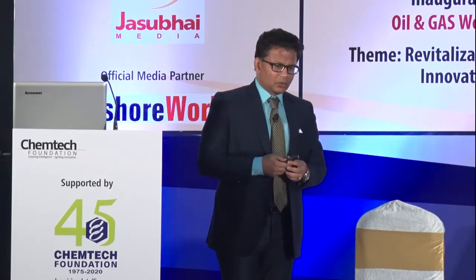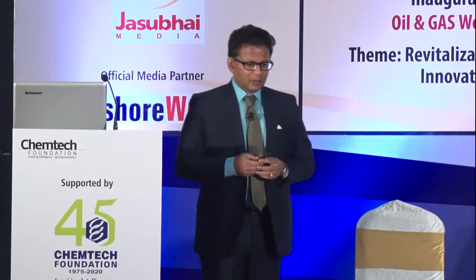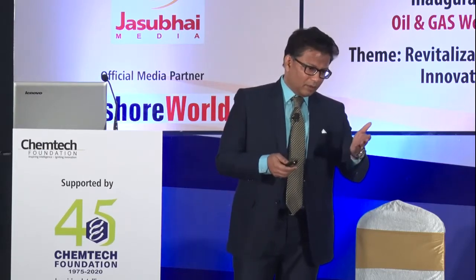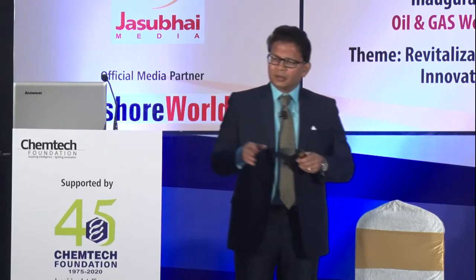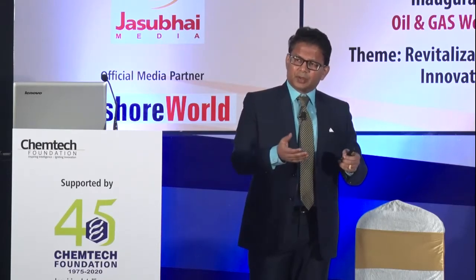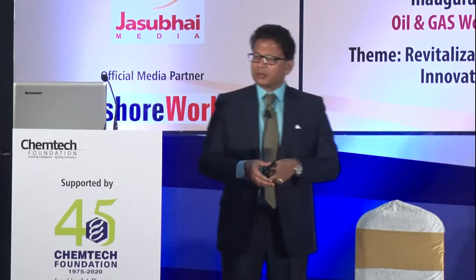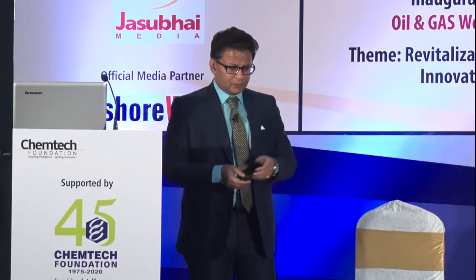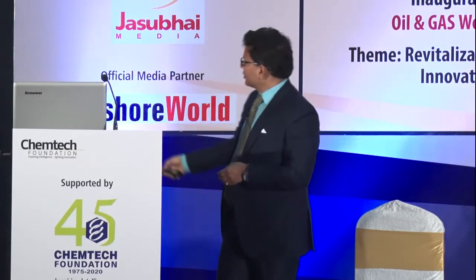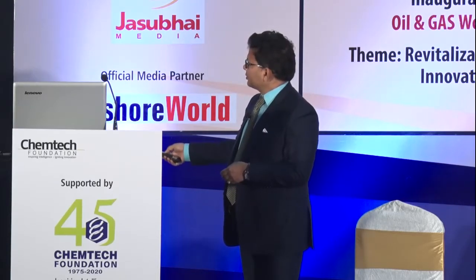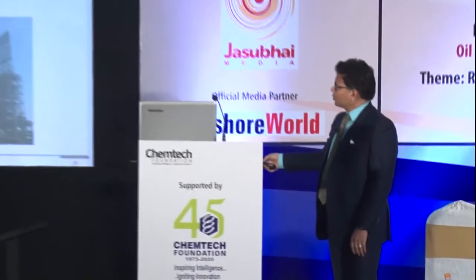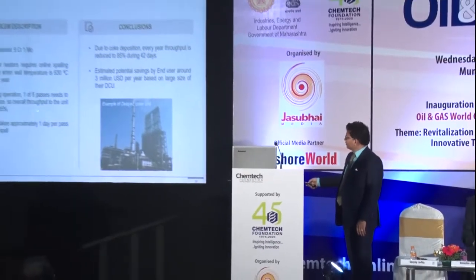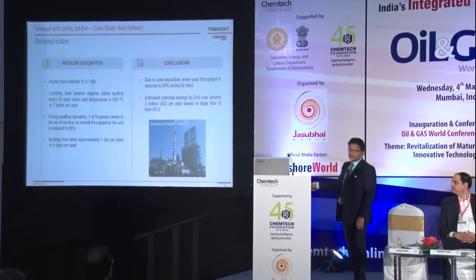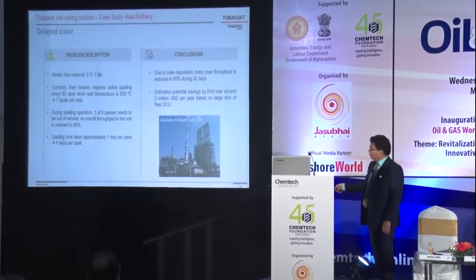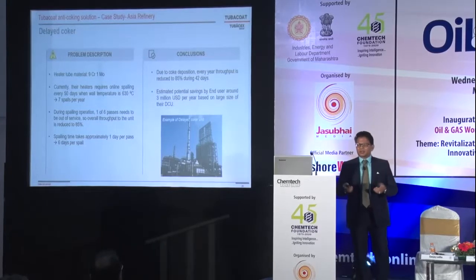This is one of the largest coker units in Korea, processing close to 50,000 barrels per day feed. And they have a P9 chrome tube, which is very common. For the delayed coker furnaces, you have P9 or P11 or 347H material. And this one had a spalling, as you can see, every 50 days. They have 6 passes, so they have close to 7 spalls per year. And during that time, the throughput is reduced to 85%. So about 42 days in a year, they run 85% throughput.